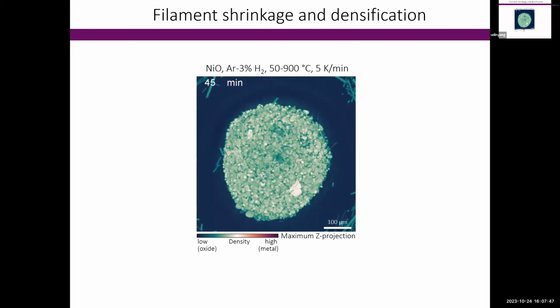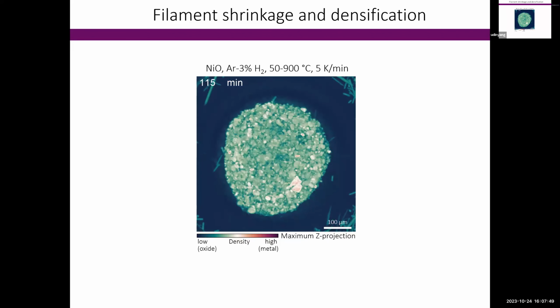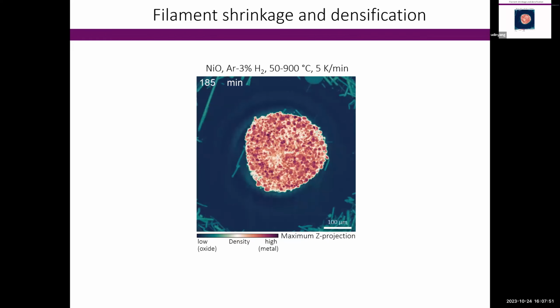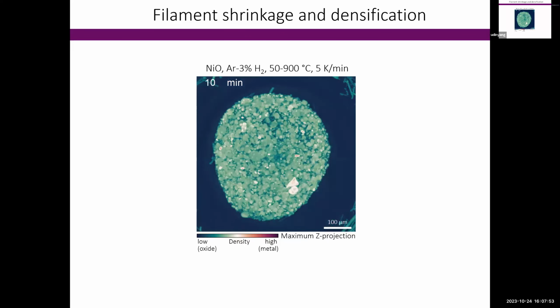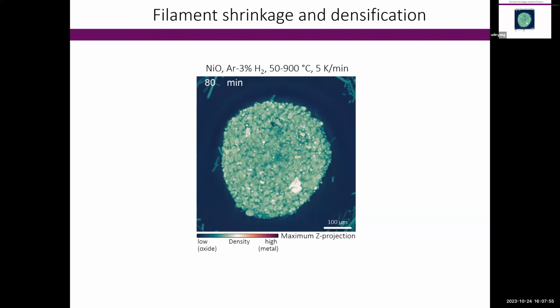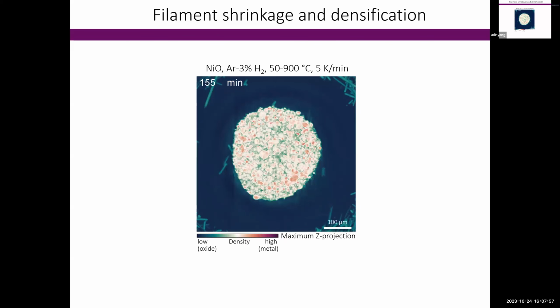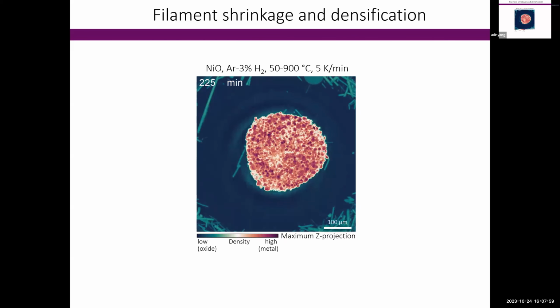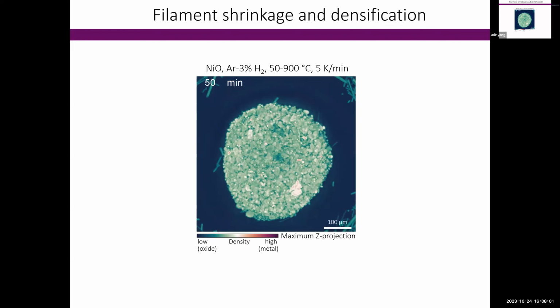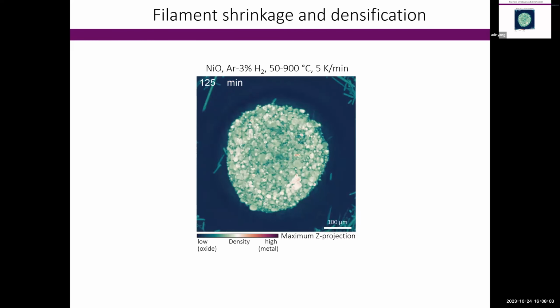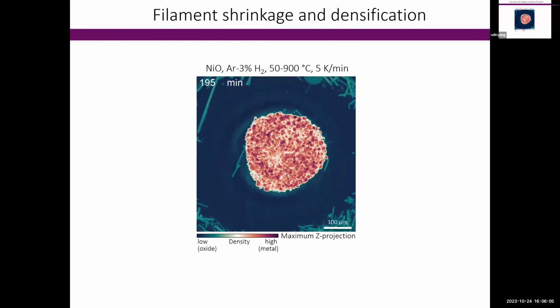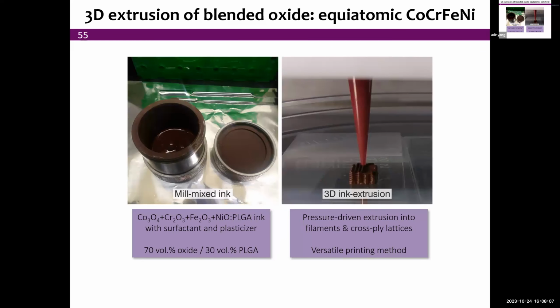So for particles that are relatively coarse, we may not see individual particles, but we will see islands, regions that are denser or less dense. And this combined with the overall shape, right? The envelope shape gives us information on the kinetics of reduction in that particular case.